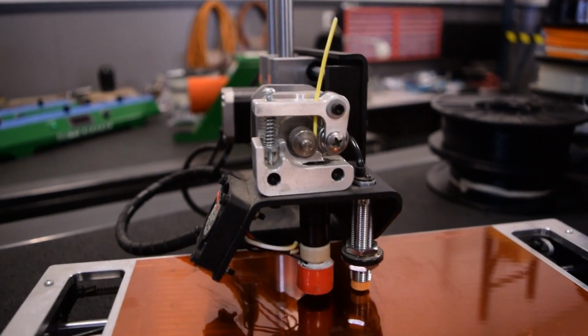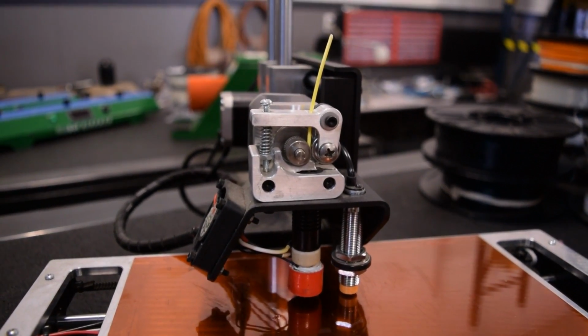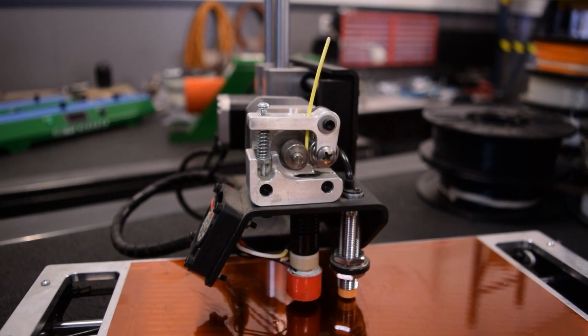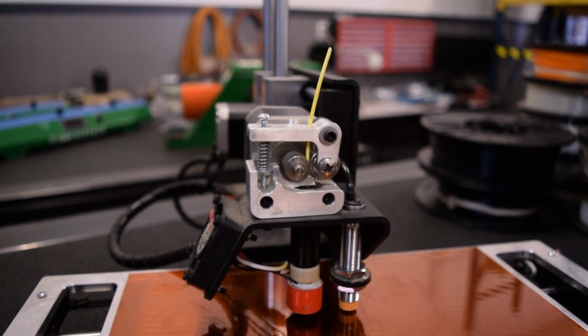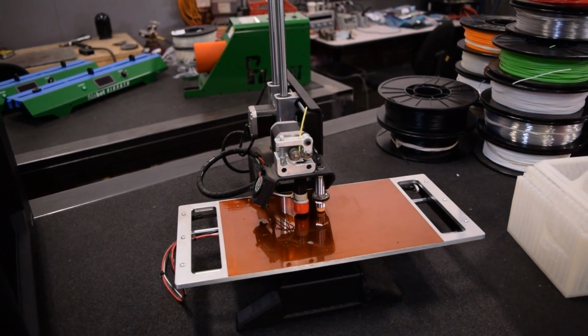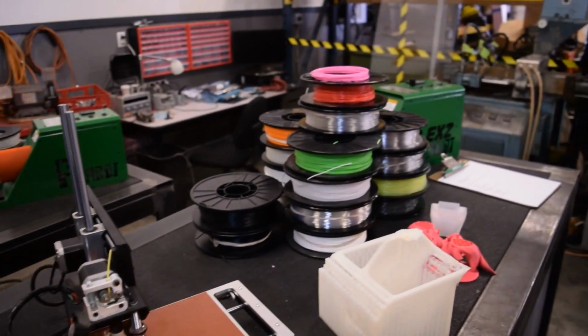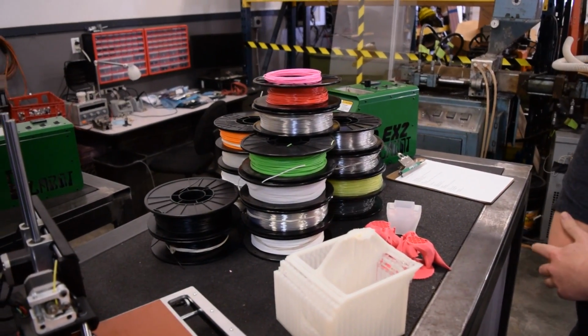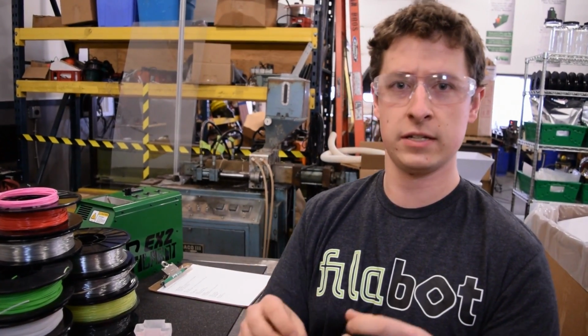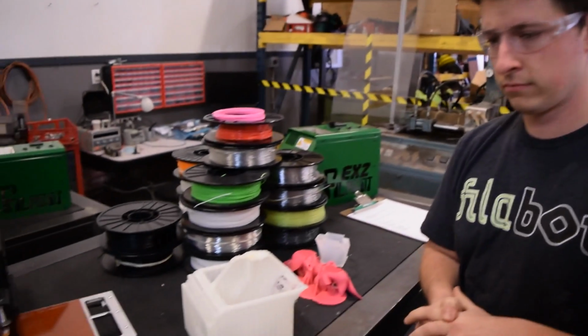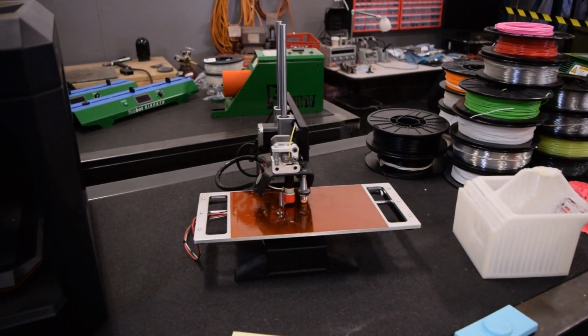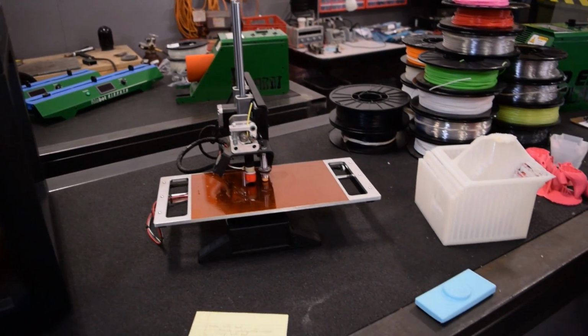Okay. So I guess one of the first issues that I actually forgot to write down is if you have some debris in your filament. So debris could be either contaminants like dust and dirt, or even a different type of polymer. Right, if you have filled polymers, like a carbon fiber or wood-filled material, and your nozzle size is too small, those fibers inside the plastic will build up and jam your nozzle. Yep, and you can also have contaminants like dirt that you don't want in there, other types of polymer and dirt.